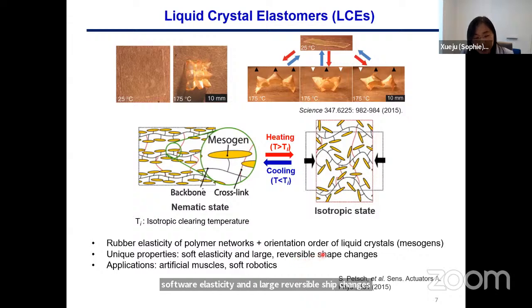The reversible shape changing behavior is closely coupled with a reversible state transition of liquid crystals, also called mesogens. For example, to program mesogens on liquid crystal elastomers for actuation, we first align the mesogens along a direction called a director into a state called a nematic state. Heating above a temperature called the isotropic clearing temperature will disrupt this mesogen order into an isotropic state and drive the macroscopic shape changes. This state transition can be reversibly realized, so that we can have the reversible shape changing behavior upon cooling and heating across the isotropic clearing temperature of the structure.